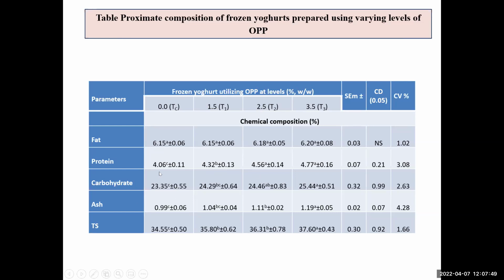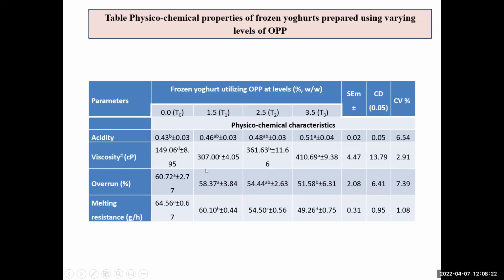As well as this, 1.5, 2.5 and 3.5% OPP. So definitely as the percentage of orange peel powder increases, there is an increase in the protein content, as this orange peel powder consists of about 5.7% protein. The carbohydrate is also increased, ash is also increased, and the TS is also increased. As the level of orange peel powder increases, there is an increase in the protein, carbohydrate, ash, as well as the TS of the product. So these are the compositions.